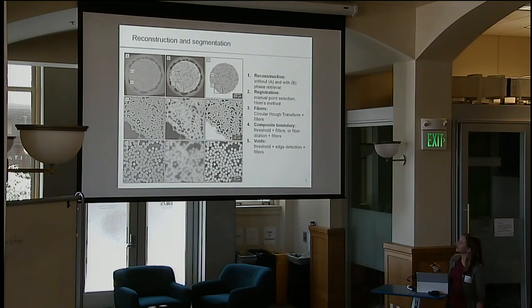So the reconstruction and segmentation is shown here. The first stage is to reconstruct the 3D volume. And for this analysis, we actually use two different reconstructions depending on what we want to segment. The reconstruction shown in this column is without phase retrieval, and in the next column is with phase retrieval. The registration is then done between data sets over time using Horn's method and then translating the 3D volume.